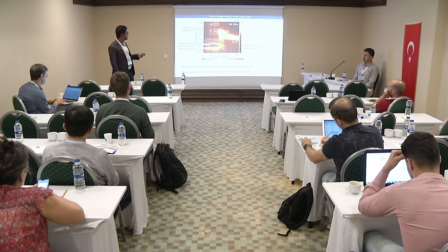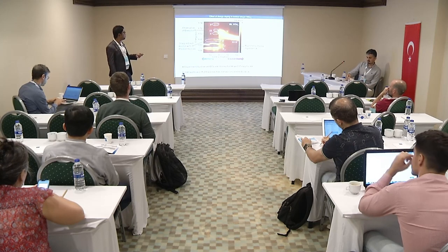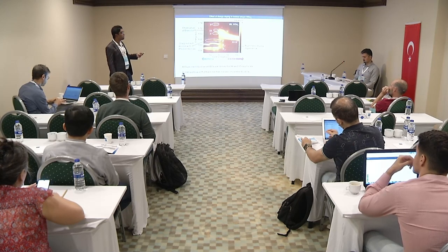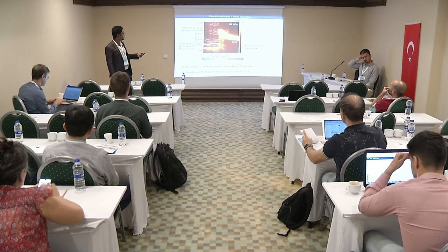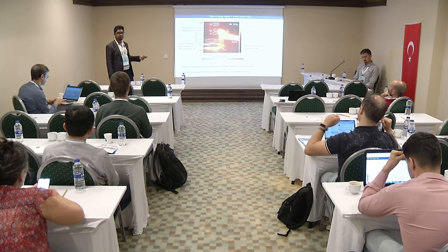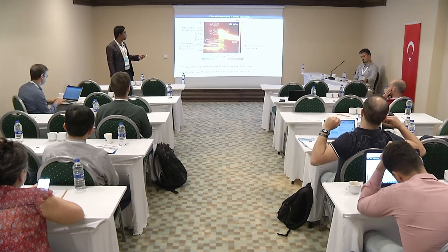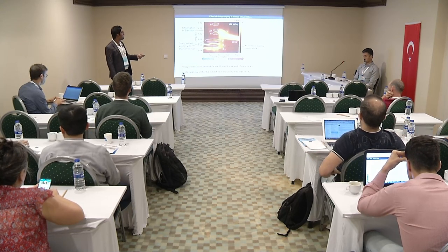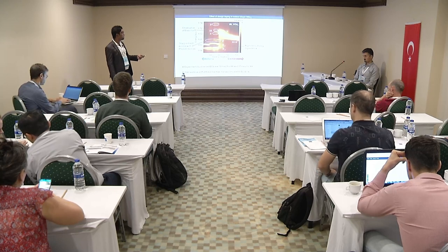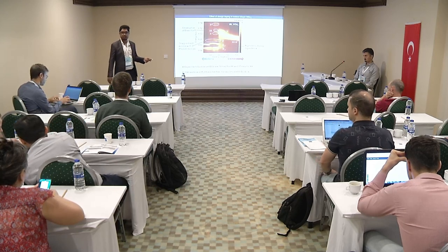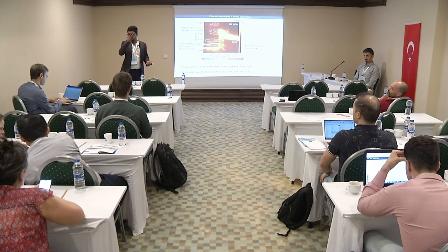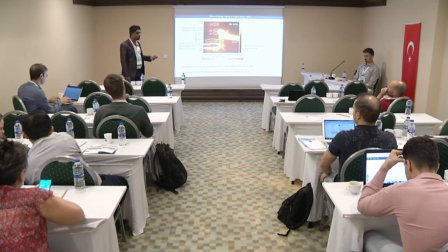Yeah. It's because at higher density, the oscillator strength of the trion is basically converting to the biexciton. That's why the X minus basically vanishes after some gate voltage and is overwhelmed by the biexciton. And another thing is that at very high doping, the biexciton is also dominated by the charged species, X double minus. These are all verified through magnetic field dependence. Okay, I see. Thank you.